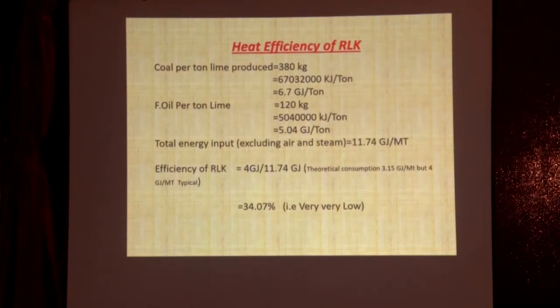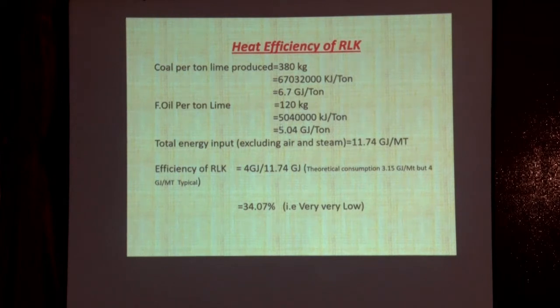This is the efficiency of the rotary lime kiln. Per ton, a typical fuel consumption in the rotary lime kiln is 4.2 to 4.5 gigajoule per ton of CaO. And the theoretical fuel consumption, as I have already mentioned, at 80% purity is only 2.6 gigajoule per ton of CaO. So what is the efficiency of the rotary lime kiln? You can calculate. We have taken 4 gigajoule consumed as 100%, though it is not theoretical. So this lime kiln is running at a low efficiency of 34%. Out of 100 we are getting only 34% marks. This is just the passing marks.